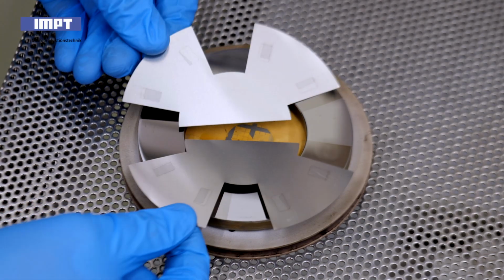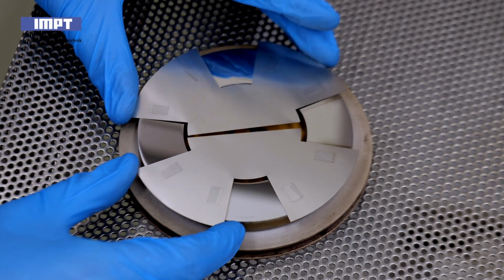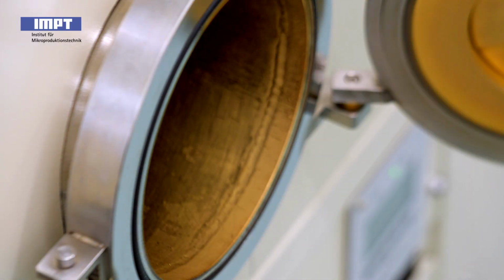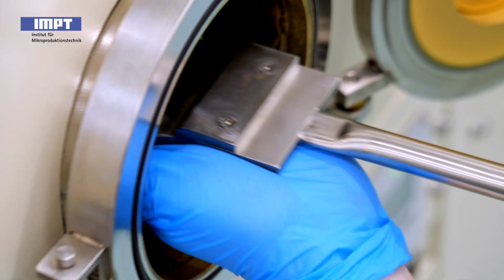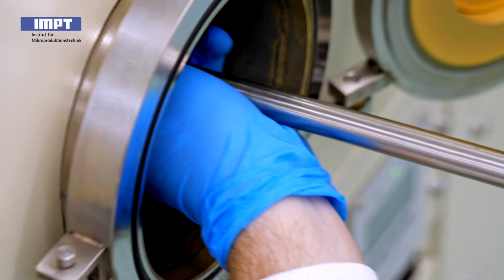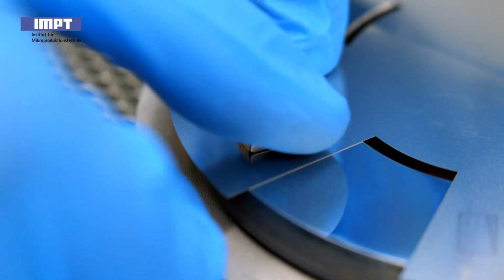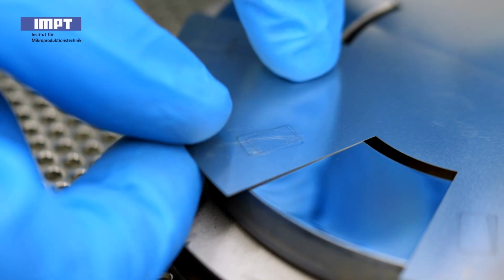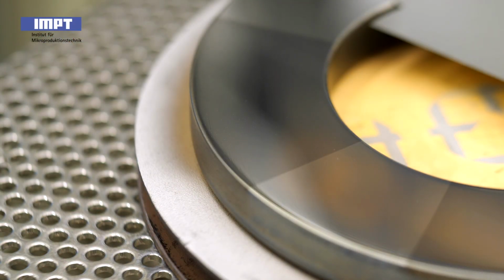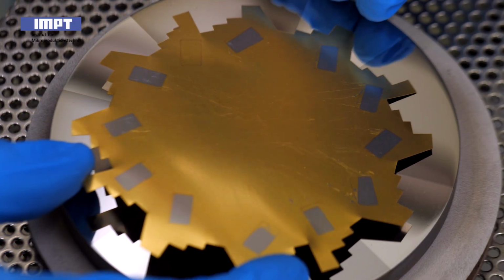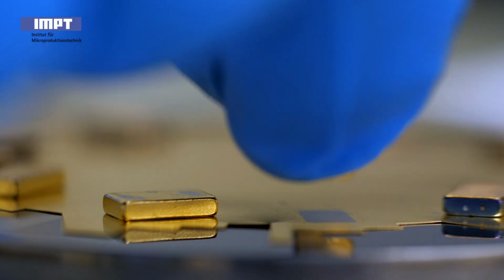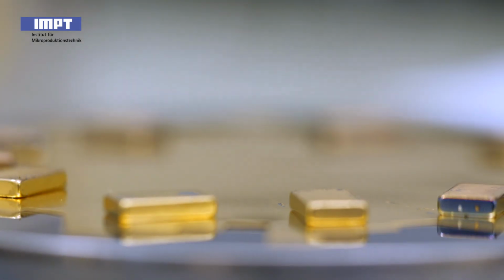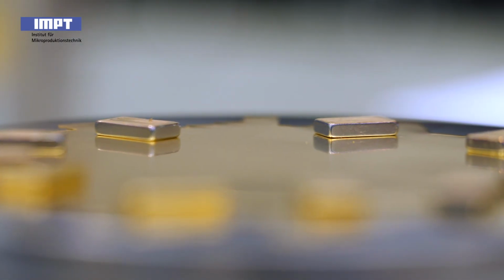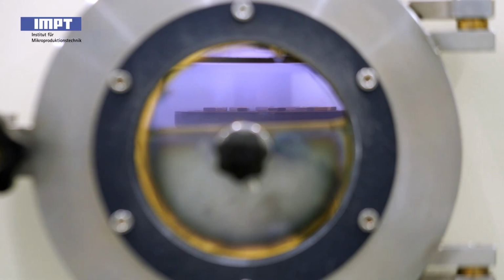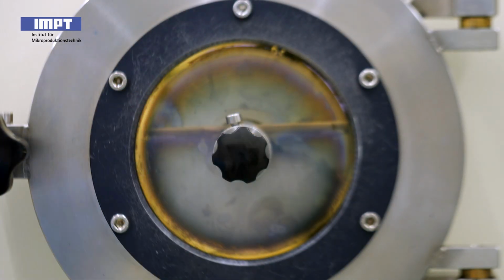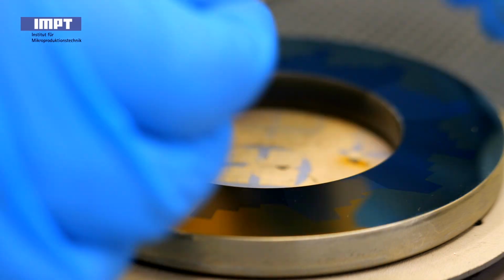For the temperature sensors, platinum is used. It has a high TCR value, which enables precise temperature measurement. However, to ensure that the platinum adheres reliably, a thin layer of titanium is first deposited as an adhesion promoter. In the final step of sensor material deposition, gold is applied using another shadow mask to the outer area of the bearing washer, where the conductor tracks and contact pads of the sensors will later be created. Here, gold significantly reduces the lead resistance and allows for reliable contacting later on by means of soldering.